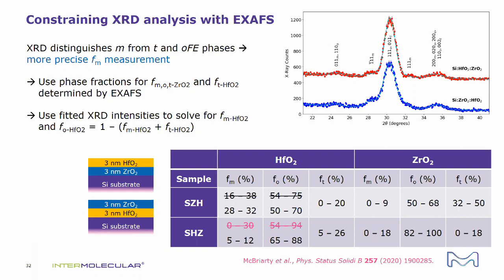We found that there was not really degeneracy, but some of the fits were quite close to each other in terms of the overall quality of fit. That's because some of the structures were quite similar to each other. From there, we came up with a feasible model for which vacancy configurations we might have, but we weren't too strong on our conclusions about exactly which vacancy configuration it was. But what each of these best fits shared was the double corner sharing vacancy configuration, and we thought that was a much clearer result.